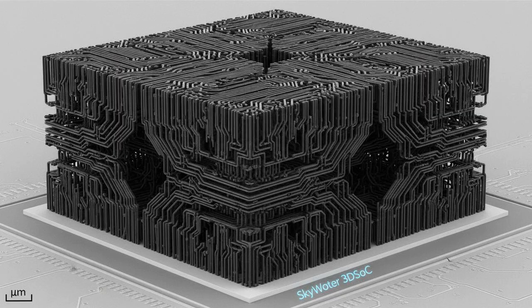Another material making science fiction a reality is carbon nanotubes, or CNTs. The Skywater Technology Foundry, in collaboration with MIT and DARPA, has been developing a 3D SoC platform using carbon nanotubes. CNTs can be deposited from a solution at room temperature and are naturally high-performance semiconductors. The Skywater breakthrough demonstrated a process where a bottom layer of standard silicon logic is covered with multiple layers of CNT-based logic and RRAM memory. Because the CNTs are processed cold, you can stack many layers without damaging the bottom. This is one of the few M3D technologies that has moved from lab curiosity to foundry prototype.